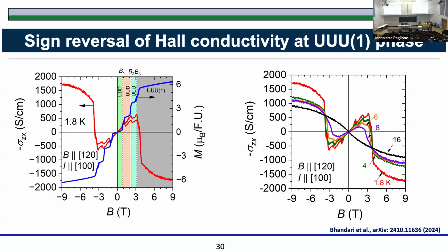Okay, and then these jumps, 1, 2, 3 jumps, don't change the magnetic structure. It flips the spin, but its magnetic unit cell remains the same. And then when you flip the blue atoms that were in the chain, it goes into a 1 by 1 structure, meaning that its magnetic unit cell becomes similar to the structural unit cell. So your bands become similar to those in the non-magnetic state, and you are recovering that electron pocket. That's how you're getting this kind of huge drop here.